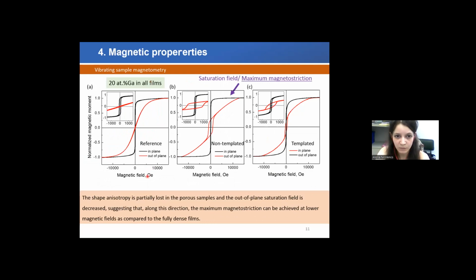Okay, in terms of magnetic properties, we focused our attention on these three films that have the same gallium content in the composition, but different porosity levels: fully dense, nanoporous, and microporous or highly porous iron gallium film. We can observe that all of these films have soft magnetic behavior with very low coercivity, and they also have an in-plane easy axis. So it is easier to magnetize these films in plane rather than out of plane. The porosity causes some changes in magnetic behavior when measuring out of plane, but I will not go into a lot of details trying to explain that and will focus more on the in-plane changes.